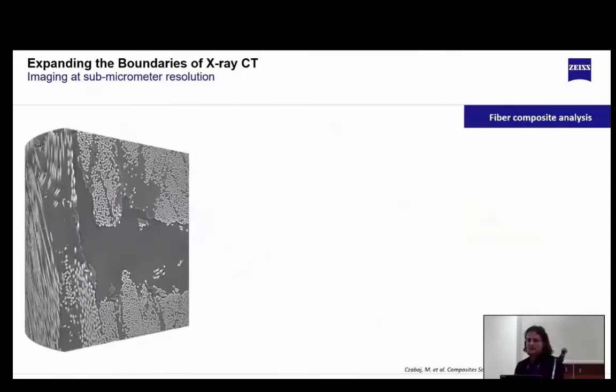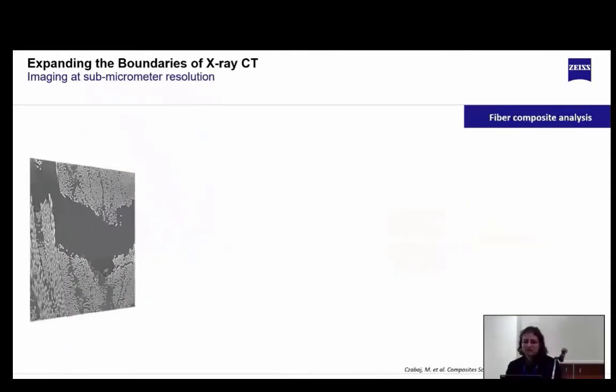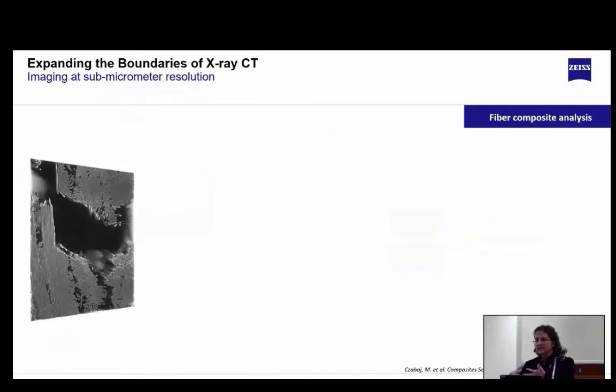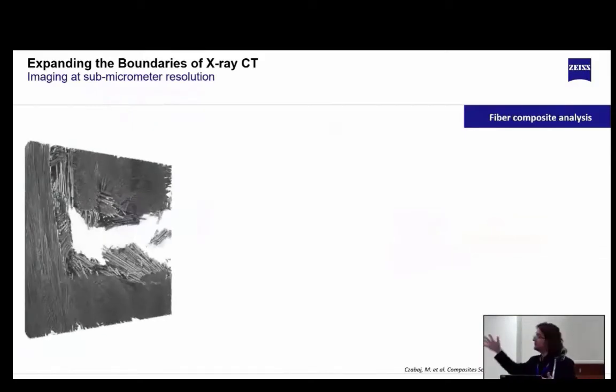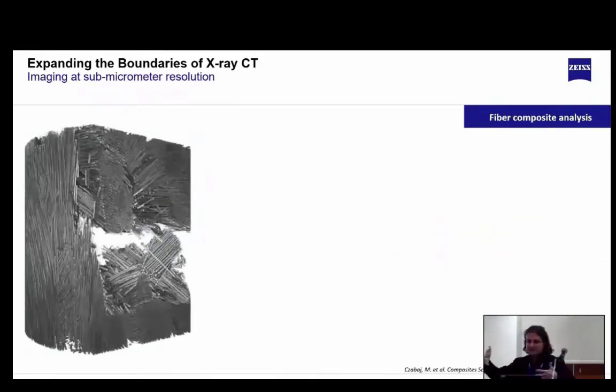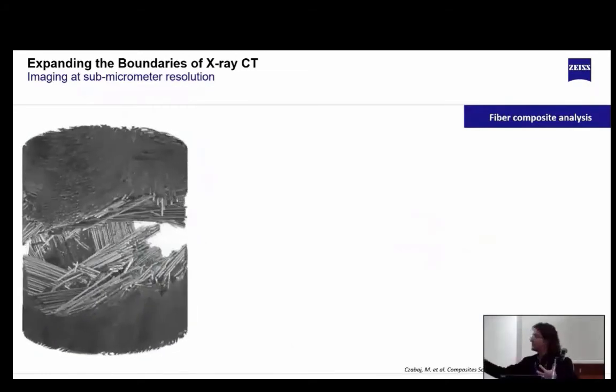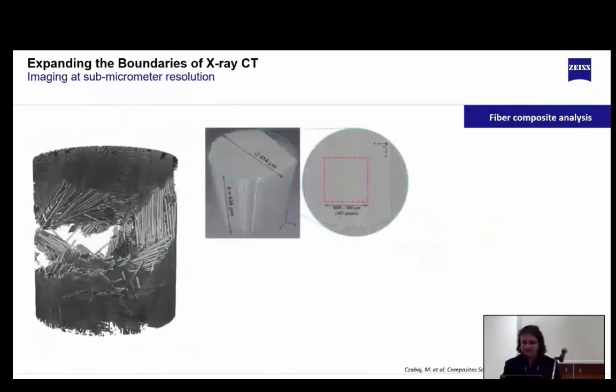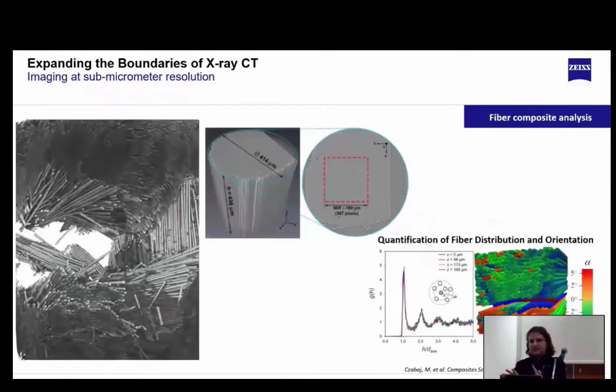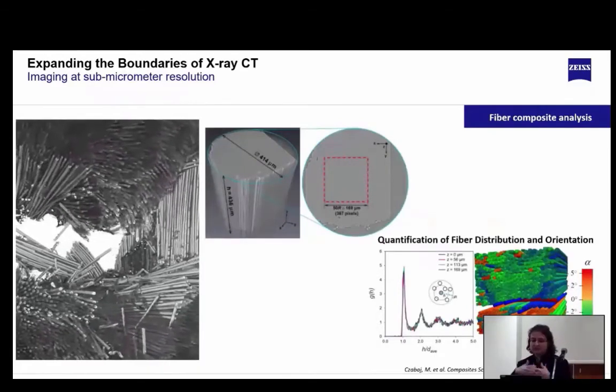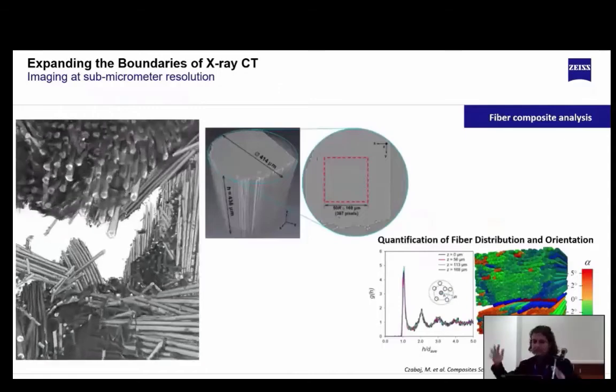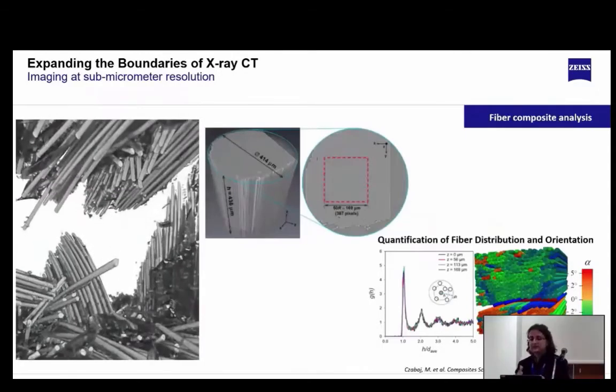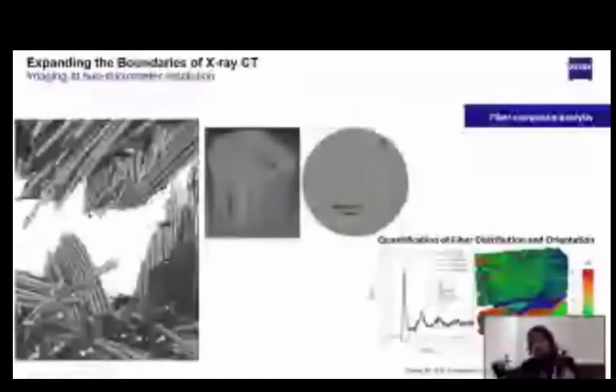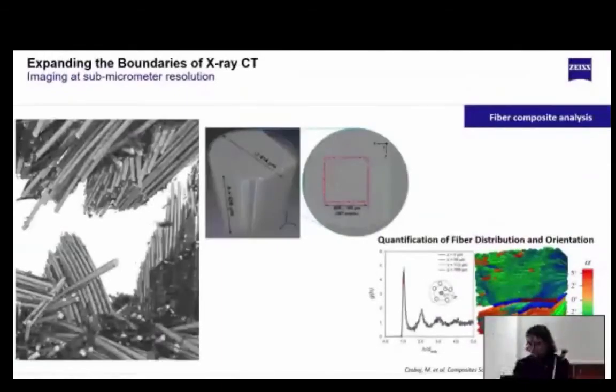The same can be done with a fiber composite sample, in which the orientation of the fiber is important and can clearly be seen in this video through virtual sectional cuts and the 3D reconstructed volume that you see over there. In addition to being able to create this nice visualization of interior features and videos, quantitative analysis can be done, such as quantification of the fiber orientation and distribution, and creating a color map based on the diameter and orientation of those fibers.